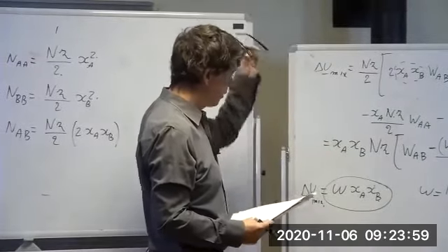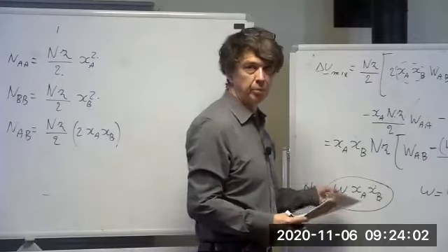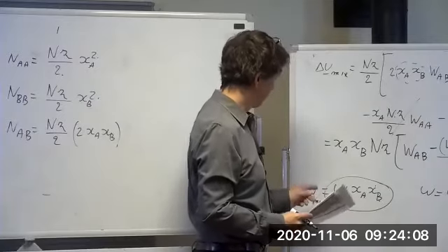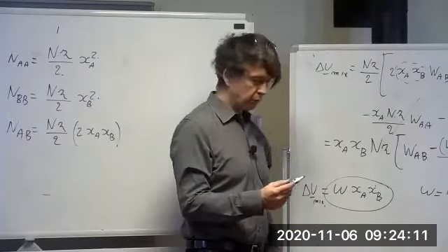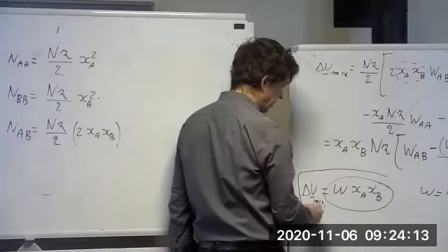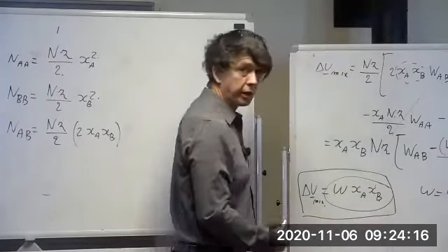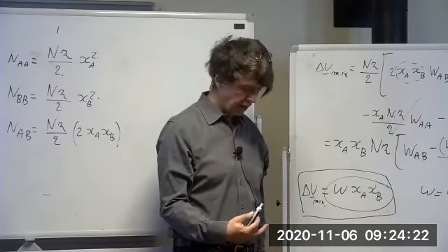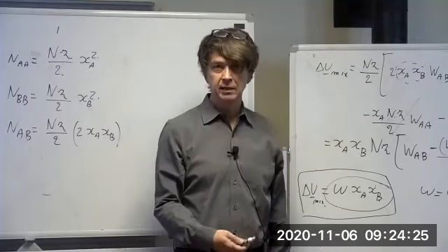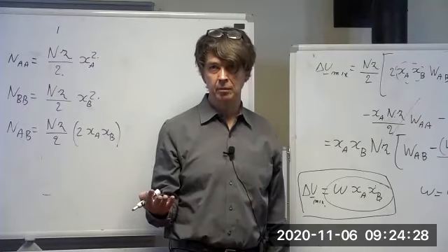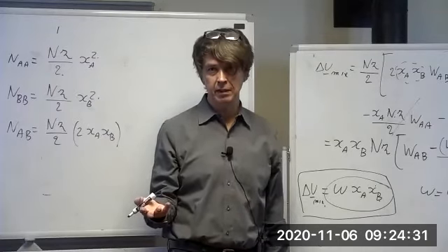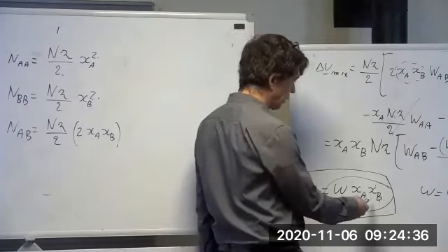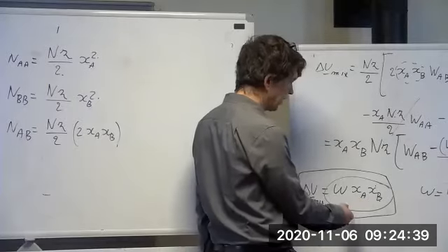But, you know, again, go through this derivation at one point, but don't lose sight of the forest for the trees. In the end, what do we find? What we find is that in this simple model, the energy of mixing is a quadratic in the composition. And it has to be, right? Because a quadratic is the simplest function that is 0 at pure A and at pure B. Because the energy of mixing has to be 0 at the end members because I'm not mixing anything. So I can't keep any linear terms. So it is the simplest function, a quadratic in XA and XB.